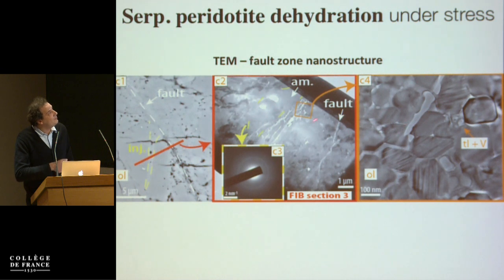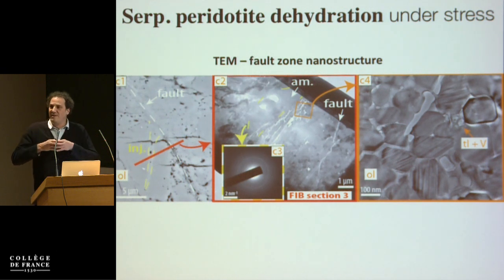And in fact, just next to this amorphous pocket, you do have euhedral, so really crystallographically shaped nano-olivine here, that you see grow in a very regular manner that really resembles olivine that would grow in a melt. So you have the idea that in fact the fault plane must have melted during these very tiny earthquakes again. So we are talking 10 micron slip, and we were able to produce what Giulio at least would call the microbeads of pseudotachylite.